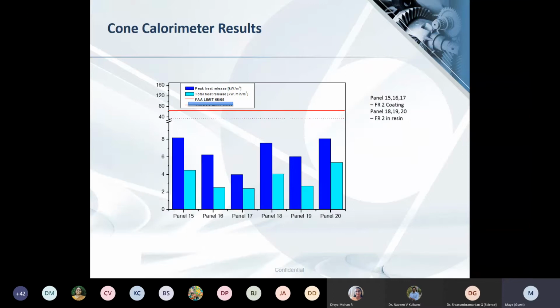Now these are the flammability results from testing done on the cone calorimeter. And here the variations in the panels are panel 15 to 17, the secondary flame retardant was applied as a coating onto the panel. Panel 18 to 20, the secondary flame retardant was added into the resin before making the panels. And all of the panels are meeting with the FAA limit, and it's actually pretty low. It's sitting at 8, while the limit requires it to be 65.